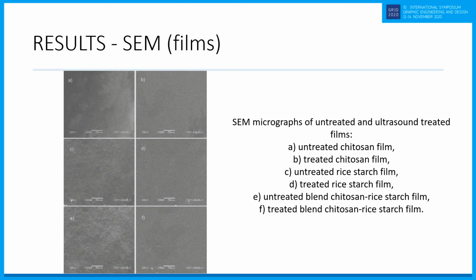Generally, the results have shown that the ultrasonic treatment caused homogeneity of the surface and is a good indicator for better structural and mechanical properties compared to the untreated films. And in general, the ultrasonic treatment can help to obtain a smoother and more homogeneous surface.